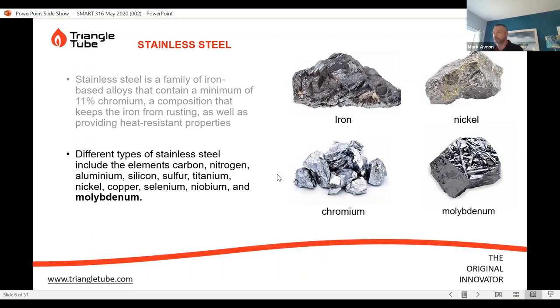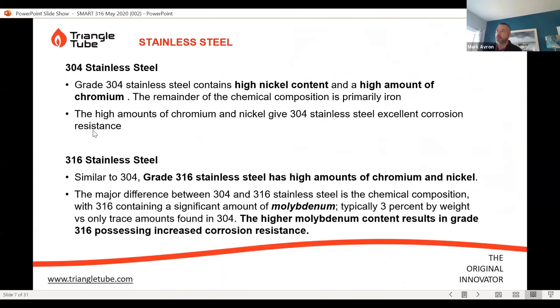So some of the elements that you might add could be aluminium, silicon, titanium, copper, niobium, and one material in particular is molybdenum, which we show on here. So that's the key ingredient to a 316 stainless, and there's a reason why. As we've started talking about making a change to 316L, the questions come up, hey, what's the difference between 304 and 316? So that's why we're presenting that today, right?